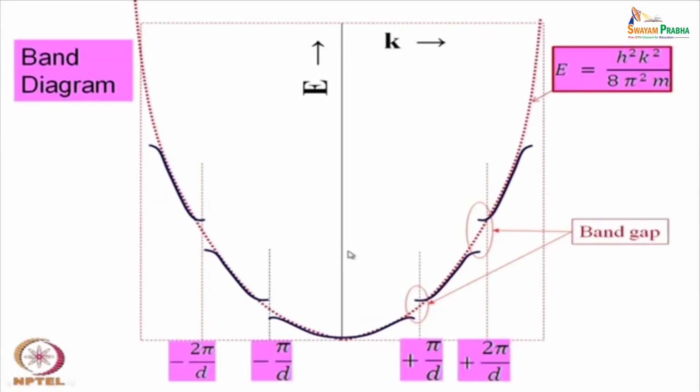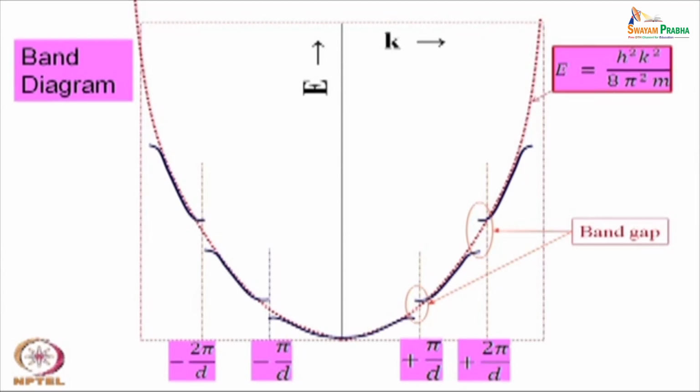This is exactly the consequence of the periodic lattice, followed by the Kronig-Penney model and the Bloch theorem. Combining all these, we finally come up with the same kind of E-k curve we observed in the free electron theory, the parabolic E-k curve which we have earlier drawn and explained. The same thing happens here also, but with some difference.